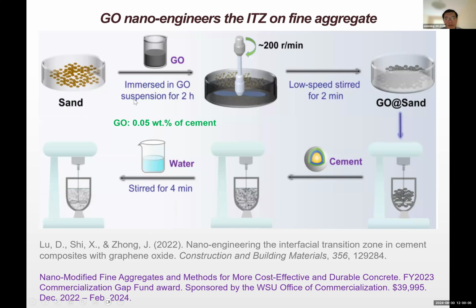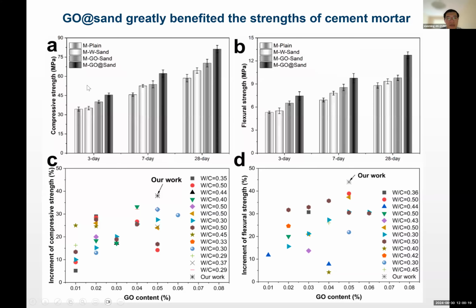Actually, this is one of the patents in review: we can treat the sand with graphene oxide ink, then dry it and put it into concrete. You can see the results here on the top. Compressive strength and flexural strength both improve. Especially impressive is that if you just mix the graphene oxide directly into fresh concrete, you get 20% or 11% in those compressive and flexural strengths. But if you actually use this new method, you get significantly better results.